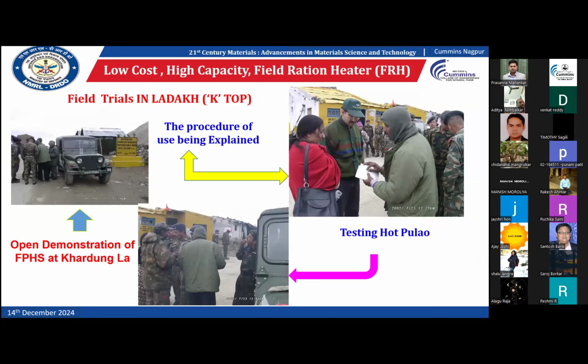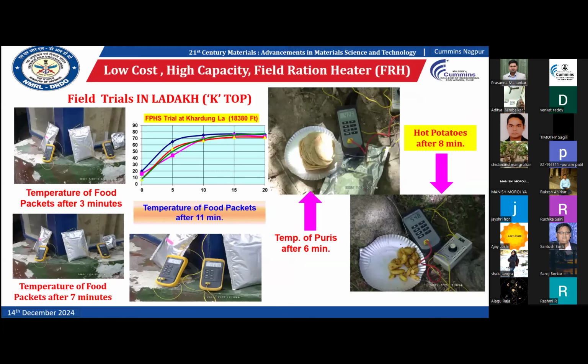Then during our demonstration, some military officers visited, so we also demonstrated that technology to those military officers. And after these army and naval applications, we wanted to check the commercial application of this product. The outside temperature is minus 35 to 40 degrees. We kept some puris and potatoes, and these puris are put in our heating pad. Add 50 ml water on both sides, and you see here in K-Top, after 20 minutes the temperature is around 80-85. So that is also successful.